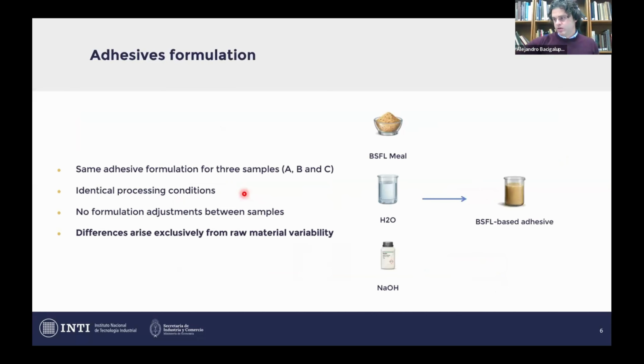For doing this, we tried to standardize the formulation and the processing conditions. You can see here the formulation. It was a very simple formulation with meal, water, and sodium hydroxide to denature the proteins. Of course, protein adhesive formulation can be very complex, but for starters, we started with this formulation. So the key is that differences in the results are exclusively from the raw material variability.